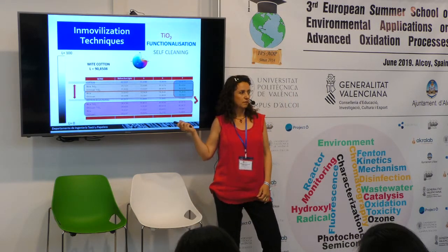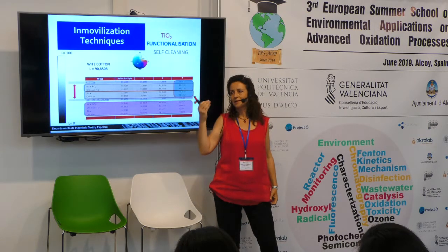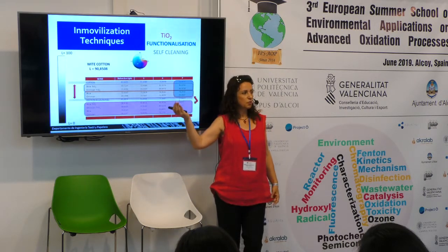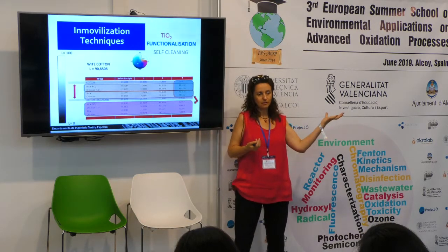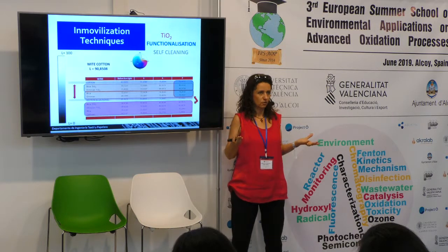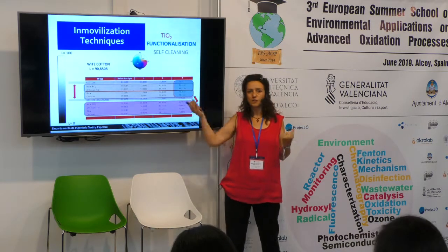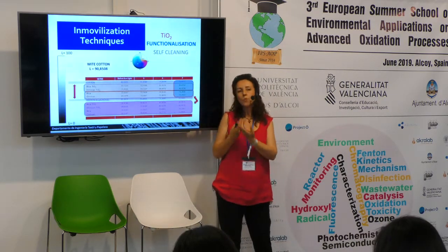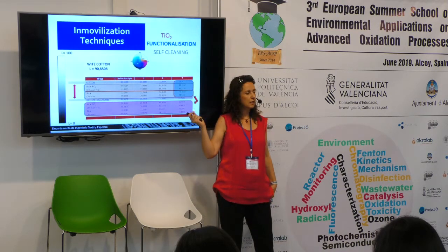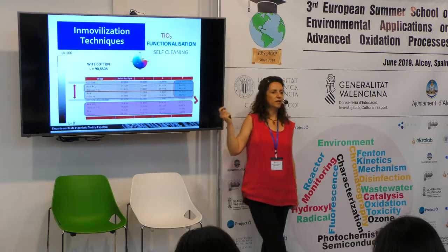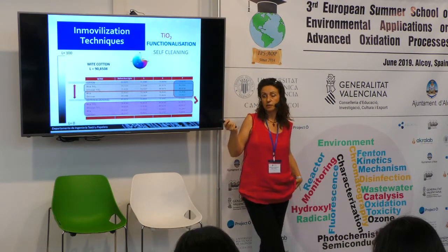What does this mean? As we could see in the first speech this morning, we had a lot of concentration of titanium dioxide. So we have an excess of this product, because after 10 laundries, I have missed more than 50% of the titanium dioxide, and the whiteness effect is going to be more or less the same.